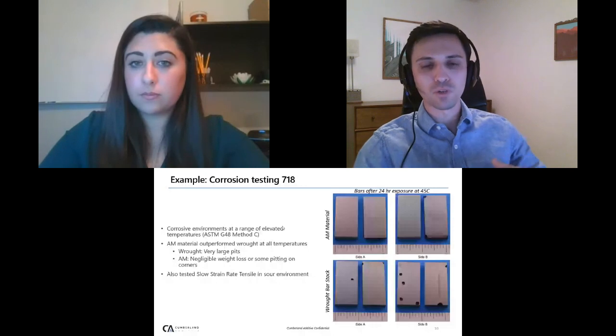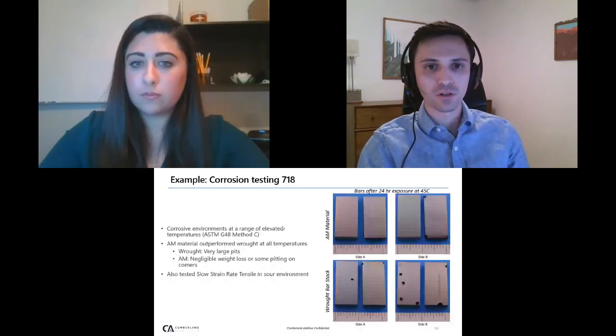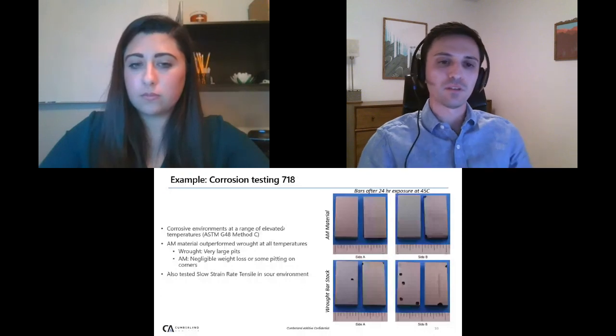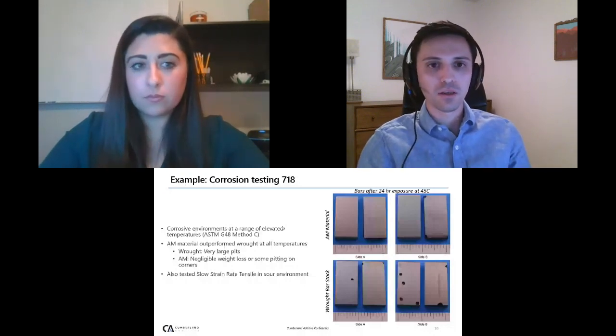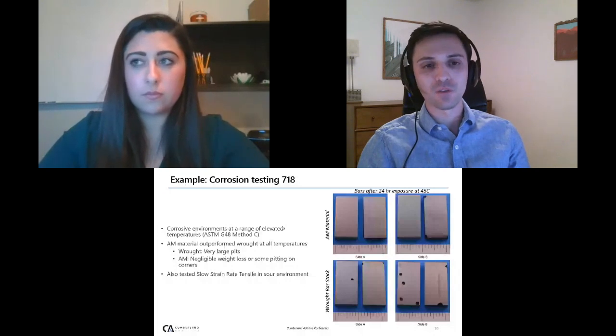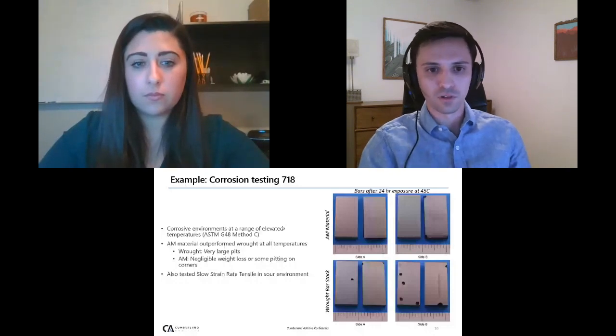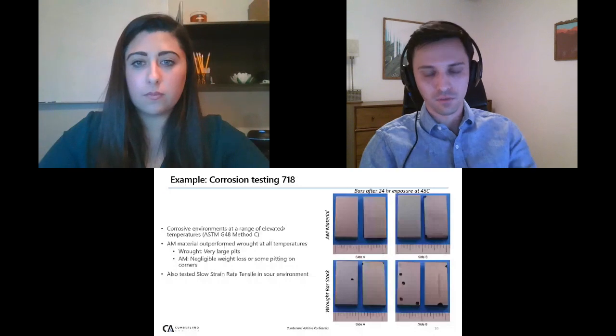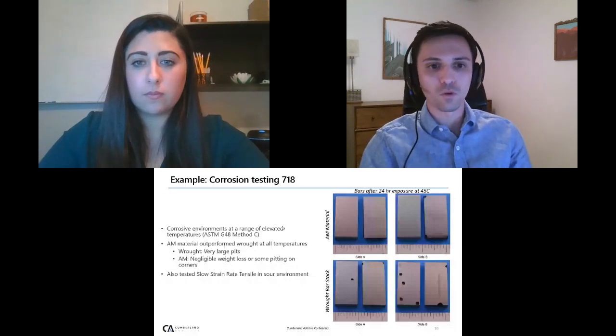So we talked a little bit about part-specific qualification and wanting to consider a specific application for a part. In oil and gas, something that might fall into that would be corrosion. So here's an example of some test specimens after they've been exposed to a corrosive environment at elevated temperature that Cumberland has done. So we tested a bunch of samples at a bunch of different environments at a range of temperatures and found that across all the specimens, the AM material, this is 718, was outperforming the raw material that was purchased as a commodity.